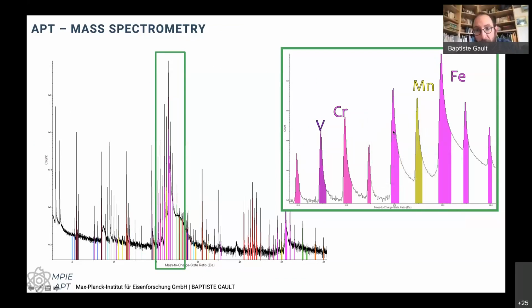So what you're saying is we should range the peaks based on the bulk composition? No, I would do one analysis with the peak ranged separately from all the rest, and then do the analysis in some of those smaller regions. In a profile, for example, I would call this peak neither chromium nor iron. I would count how many atoms there are in there, and then based on the number of chromium atoms, I know how many atoms of that range correspond to chromium. Okay. The rest has to be iron.